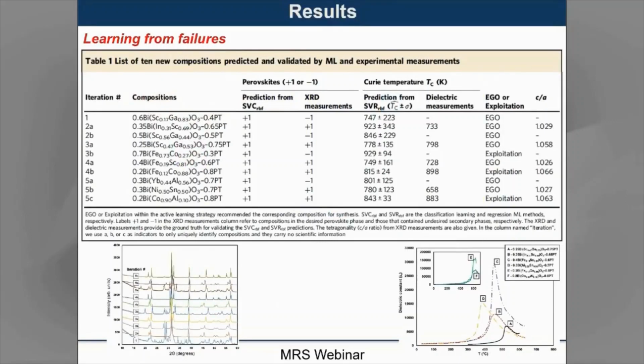So I'm summarizing the results in the slide. The key points are the following. In total, we were able to perform 10 experiments in this particular exercise in 5 iterations. And it turned out that 6 out of the 10 compositions that we predicted had the desired perovskite crystal structure. And some of the compositions even had a high ferroelectric Curie temperature of approximately 900 Kelvin.